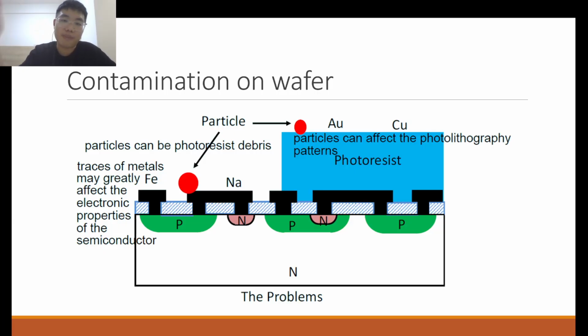For example, if you have a particle on a photoresist, it will block certain areas that should be exposed to your UV light during exposure. But the area is now blocked by the particle. So certainly it will affect the photolithography patterns that are patterned onto the wafer during the development step. In addition, if a particle falls on the wafer surface, on the feature itself, it creates an inclusion, where your subsequent deposition or subsequent steps that need a certain overlay on top would definitely be affected by the presence of this particle on your features.